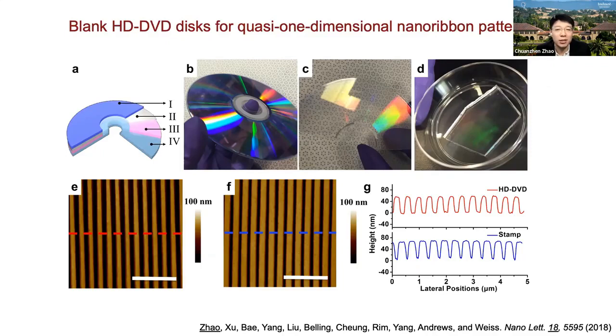Here, we developed a process using the HD DVD, basically at everyone's home, as the mold for the PDMS, and that can be used for the patterning process. Those DVDs are accessible to everyone, and they are also just a couple of dollars each. Generally, the HD DVD has a quasi-1D feature, with a width of 200 nanometers and spaced out at a pitch of 400 nanometers.